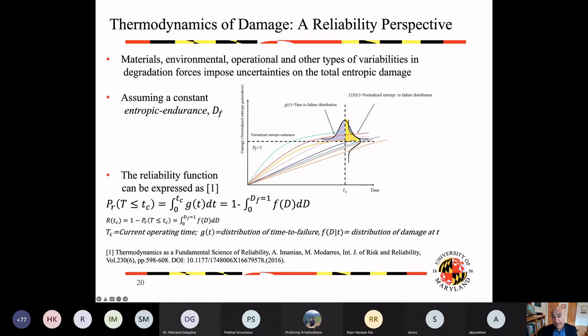At this time, if I take this cut in time, each of these points shows how much cumulative damage, due to the amount of entropy, I have. So this curve right here shows the distribution of the damage, or the distribution of cumulative entropy values, which is due to the dissipation accumulated by that time. Now the orange area, which is above the level of entropic endurance, is the cause of failure, the components that reached this level and caused a crack of 250 micron. And that's the probability that by this time they reach this point.